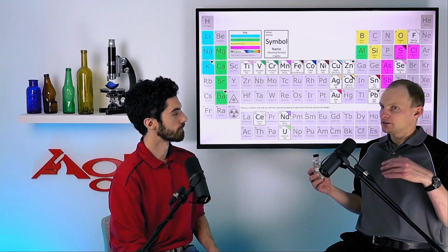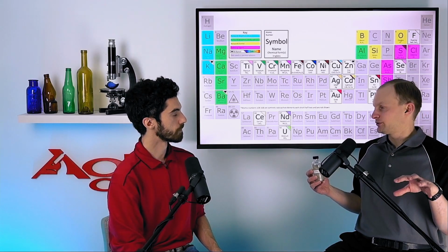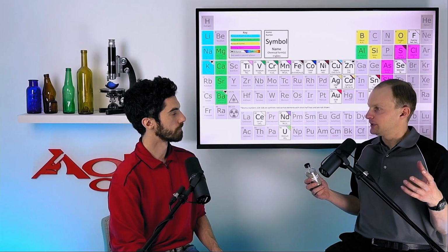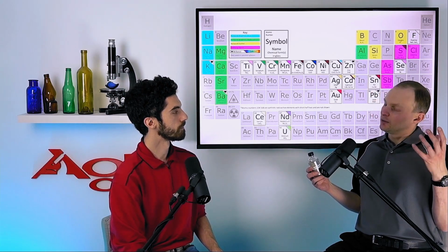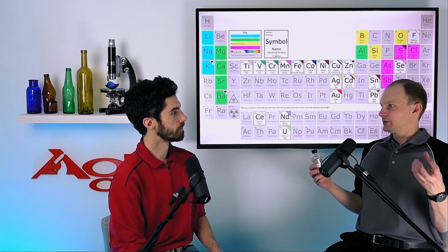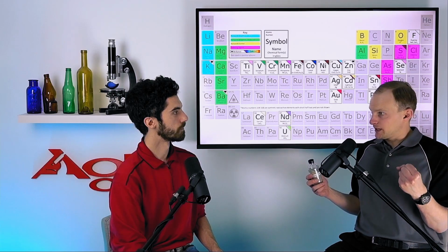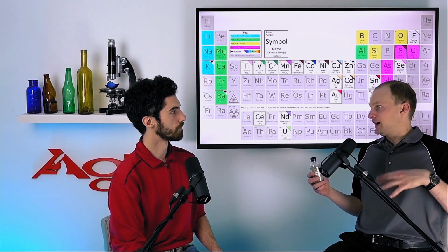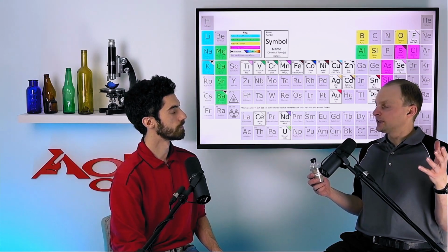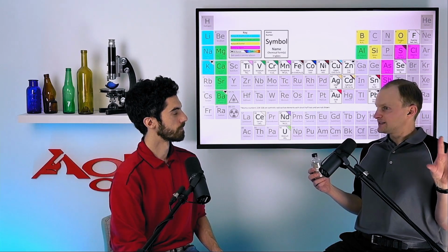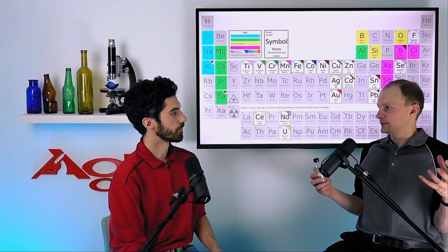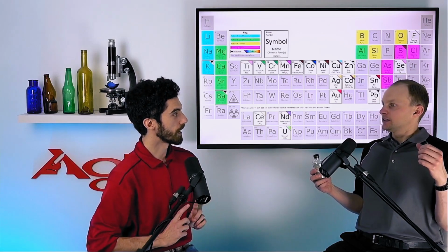When you're making iron metal from ore, you've got rocks that come out of the ground, and these rocks have iron in them as well as other silicate minerals. You're heating them up in a blast furnace, melting them, and the iron is going to get reduced into elemental iron, which sinks to the bottom of your furnace and gets drained out. Now, all the other stuff has to go somewhere, and you end up with this molten mixture of silicates, these glassy types of material that floats to the top. And that's the stuff we wanted for our glass, right? Our batch material.